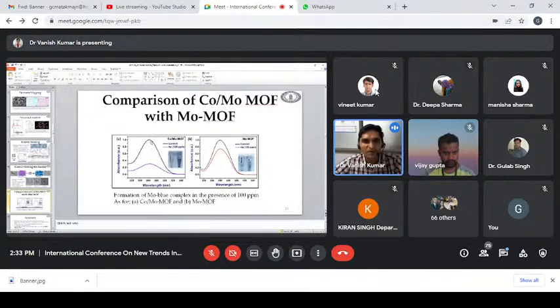So, as I told you earlier, we also tested the molybdenum-based MOF without the presence of cobalt. If you see in A, this is the cobalt and molybdenum MOF. The absorbance of this MOF decreased from 1 to 0.2 after addition of 100 ppm of arsenic. Whereas in case of B, there is no cobalt in this MOF. After addition of 100 ppm of arsenic, the absorbance of this MOF decreased from 1 to 0.7. So that's why we opted for this cobalt-molybdenum MOF for our studies, and we built this sensor for arsenic determination. So this is the summary of this work.